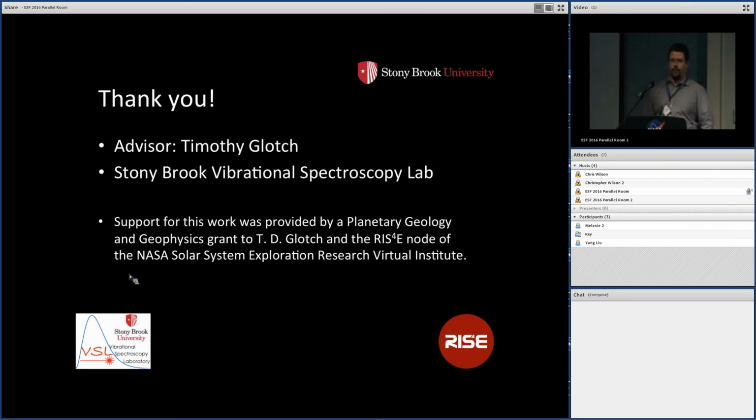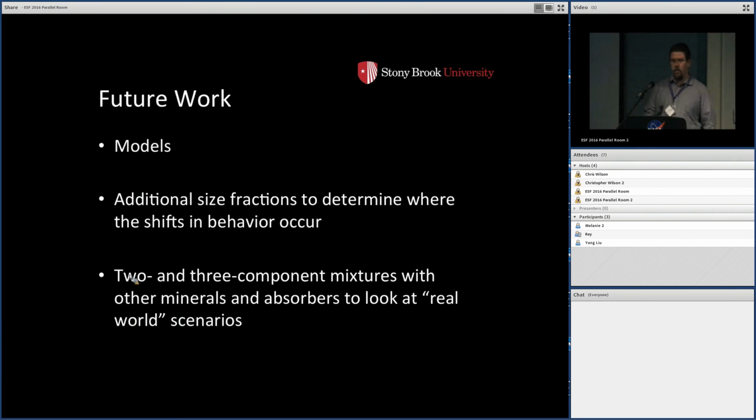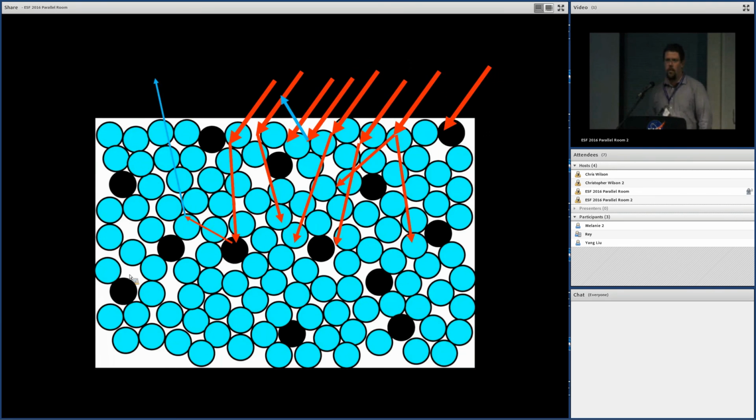And then the other thing is in your diagram where you show the voids, how you have scattering off the voids. I know it was probably just simplistic, but you must mean that it goes all the way down, hits another particle and goes out? So is every time it's scattering? Every time it crosses a particle-void interface, there is some scattering that occurs. And additionally, anytime it's traveling through any of these mediums, some level of absorption is occurring if it's not a vacuum. So every time that you leave or enter a particle, you're scattering. Anytime you hit an inclusion in a particle, you're scattering.